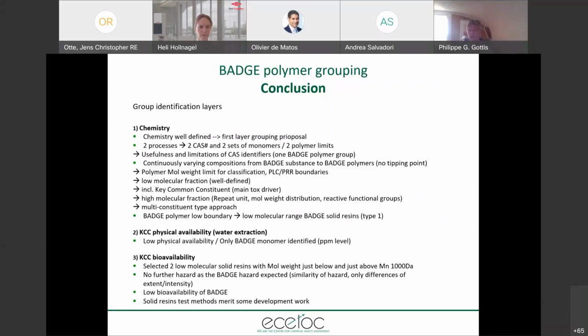for identification and grouping. The low molecular fraction, as shown in the GPC spectrum, is present in every BADGE polymer to various extent. This low molecular fraction contains well-identified constituents, including the key common constituent, which is the main common tox driver. The high molecular fraction doesn't require identification of every oligomer. It can be conveniently well-defined with the repeat unit, the molecular weight distribution, the reactive functional groups. Polymers such as batch polymers are well-defined multi-constituent type polymers.